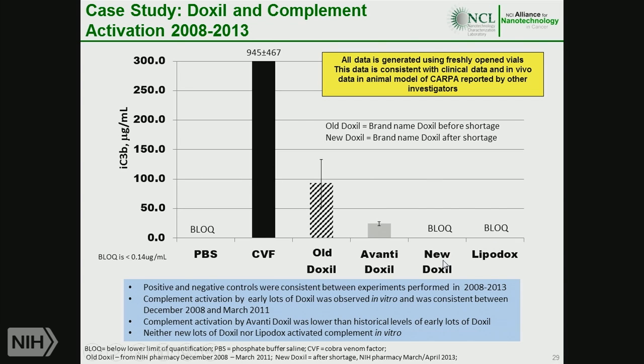Physicians that used Doxil after the shortage noticed a lower incidence of CARPA, and there is a lower propensity of this material to induce complement activation. Why does this happen? So this is a positive change, right? We had a greater incidence of complement activation related to the allergy, but when the procedure was changed and the new material was manufactured, there is less CARPA induction and less complement activation. What we can say is that this is not due to any change in particle size and particle zeta potential. There is something else, and we are currently investigating the difference to understand the mechanism.